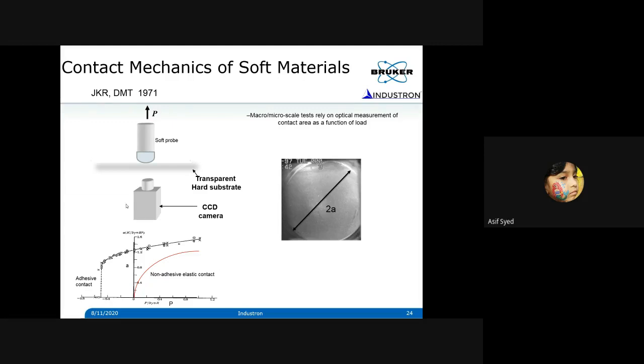By measuring the change in contact size as well as the force when you pull off, you can get a curve like this. That is what I'm showing over here. Using this curve, they modeled that whole contact mechanics. It's called JKR mechanics. Surprisingly, this formulation works even at nanometer length scale. So that is the good thing. We can use those kinds of models, but we need to modify them a little bit.